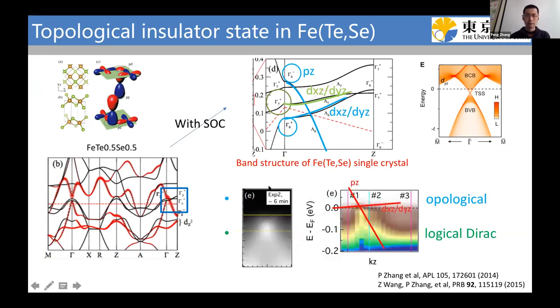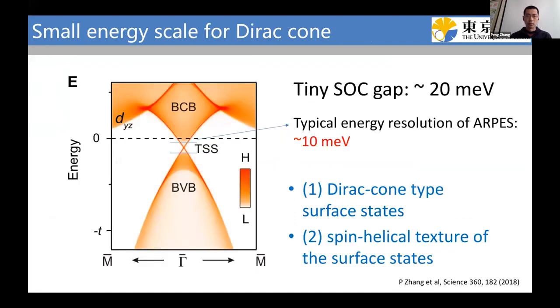At the same time, we found some evidence of the pz band. We doped the iron, tellurium, selenium with potassium, and we found an electron band originally above the Fermi level, which should be the pz band. From the kz measurement, we also see some signature of the pz band going down from the gamma point to the Z point, but we could not directly resolve the surface state at that time. The reason is that the energy scale for this SOC gap is very small. In the calculation, we found it's about 20 meV, while the energy resolution for most ARPES is about 10 meV. So it's impossible to distinguish this Dirac cone in such a small energy scale.